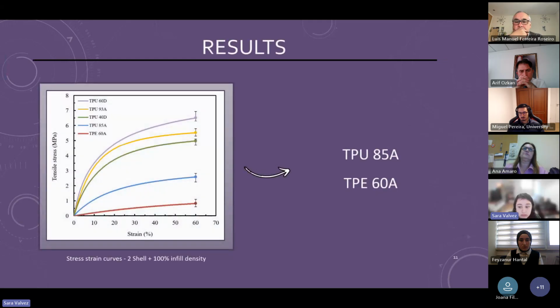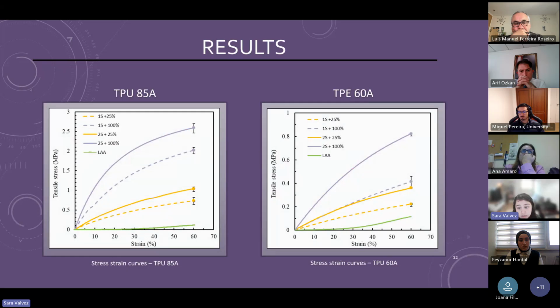So the initial results were only used to select the 2 best materials for the problem that we have in hand. The samples tested were with 2 shells and 100% infill. And according to the literature, the biological tissues of the myocardium have relatively low maximum tensile stress. So the most suitable materials, according to that range of values, are TPU 85A and TPE 60A. And then for the second part of the research, the printing parameters were evaluated.